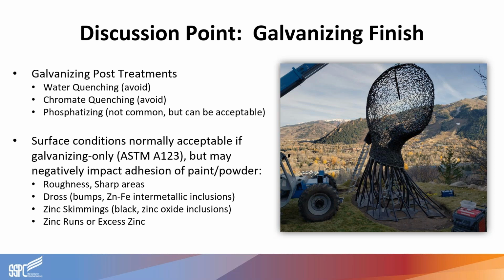When all parties are informed about the duplexing, then the galvanizer is going to be held responsible for ensuring that these passivations are not performed. Next, the elevated aesthetic requirements for hot dip galvanizing must also be communicated to all parties. Like I mentioned before, typical imperfections and roughness in the galvanized coating are often acceptable on a normal basis, but if we're painting or powder coating the galvanized surface, there are conditions which would impact the coating adhesion, and those all need to be addressed.